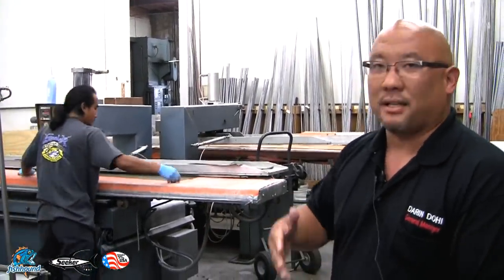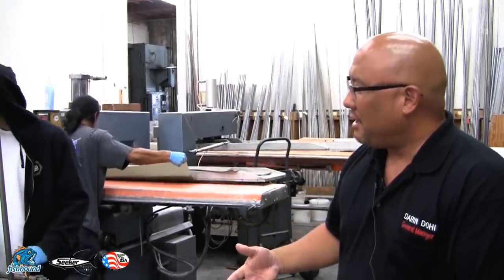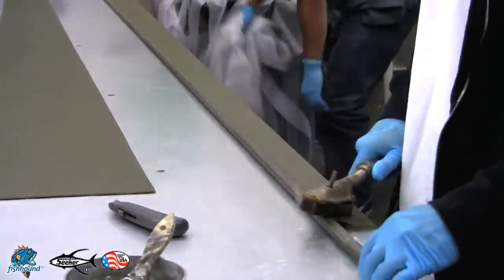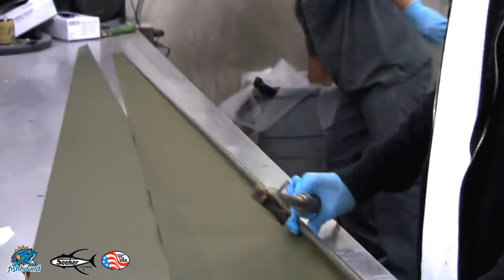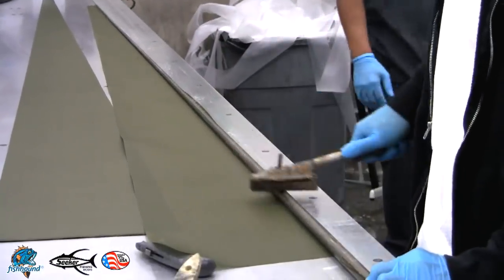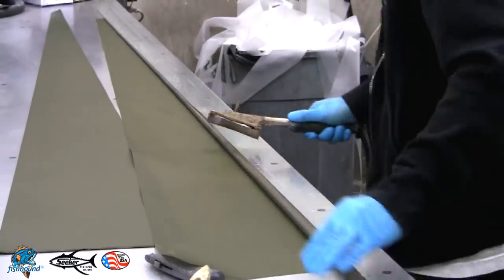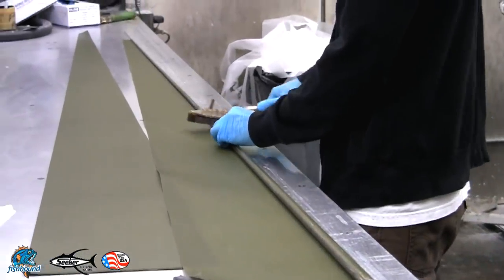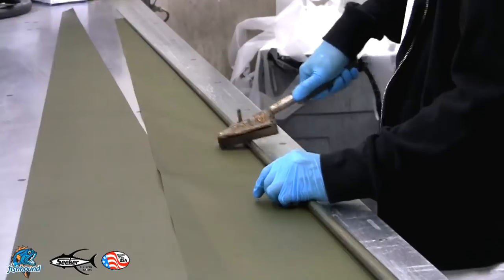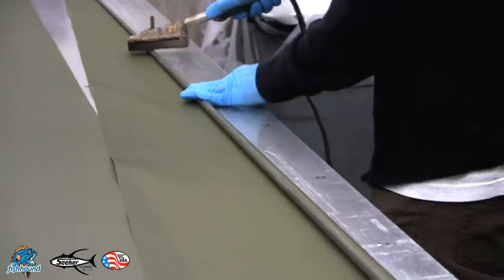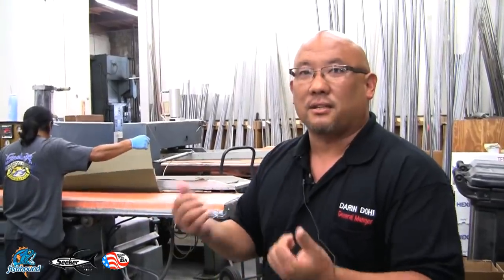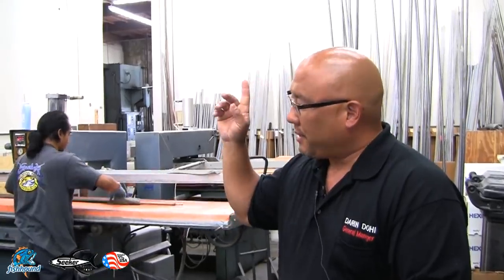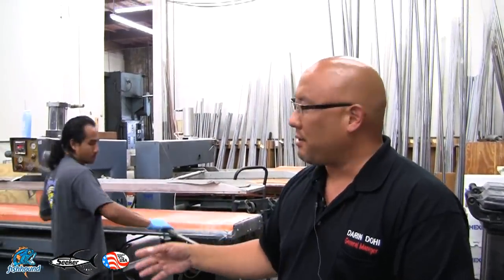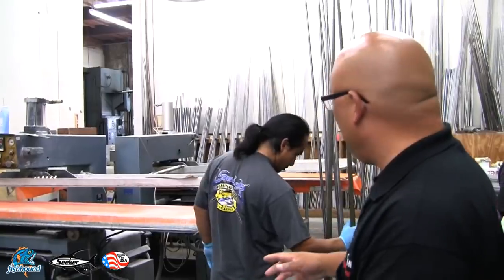The taper gives it its action, and you can see that it takes a little bit of time to get that thing attached properly. If it doesn't get attached properly to the mandrel, it's going to have a condition called loose tack. The loose tack area of the rod is going to be very weak, and ultimately it's going to have a tendency to fail there. So we take a lot of time in attaching the material to the mandrel so that we don't have any loose tack situations.